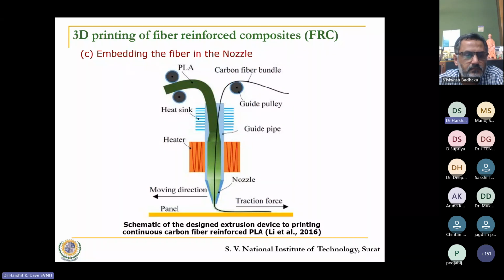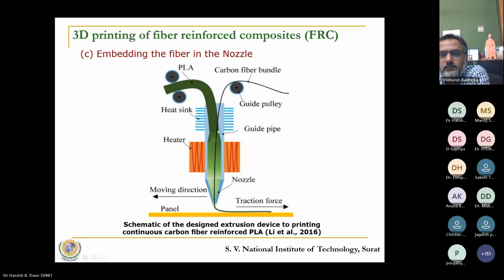The third way of creating fiber reinforced composites is by embedding the fiber in the nozzle. So what we do is we keep the fiber bundle separate. Somewhere we may have a polymer filament bundle, somewhere else we may have a carbon fiber bundle, but then they are passed through the nozzle together, and the PLA filament is slightly heated up. Of course, that does not have any effect on the carbon fiber. And when they come out from the nozzle, they get deposited on the surface together.